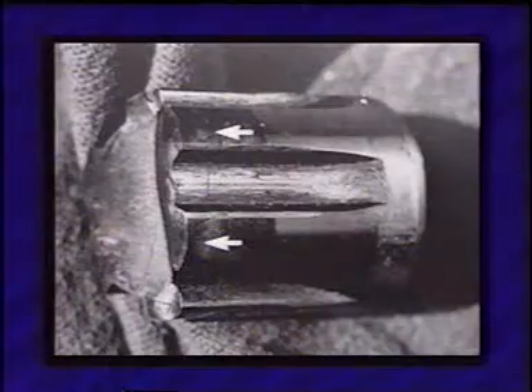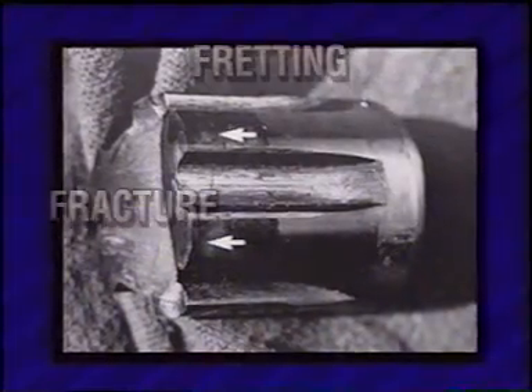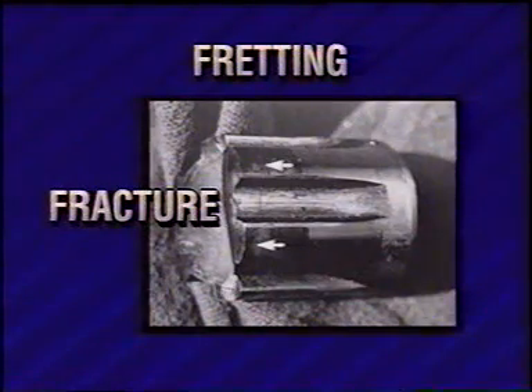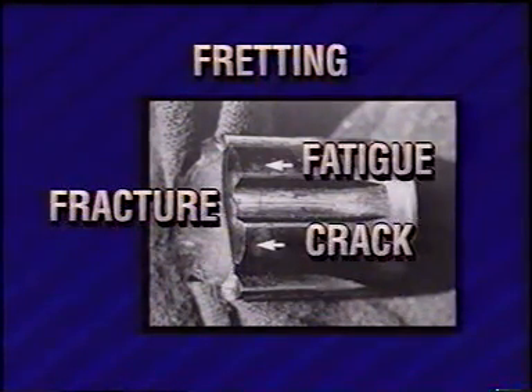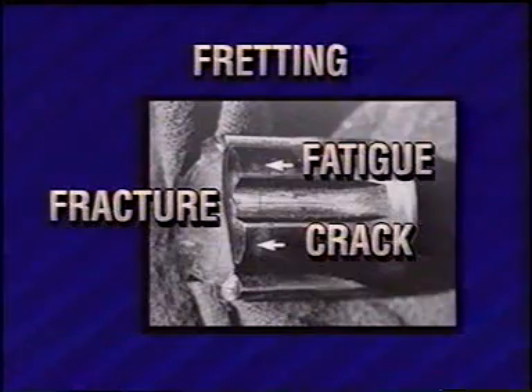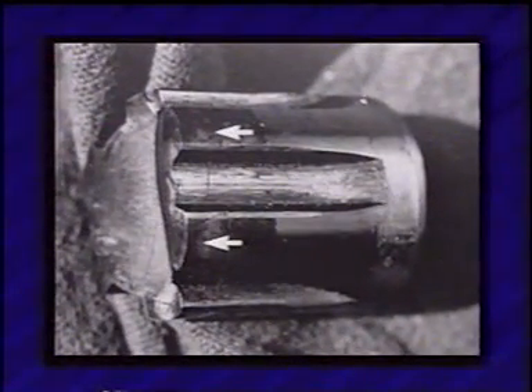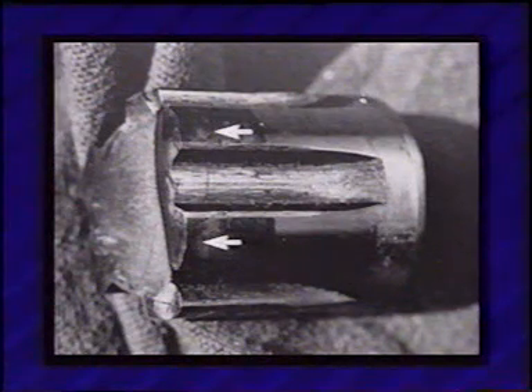One of the major problems with fretting is not the destruction of the joint itself, but the fact that it frequently leads to fatigue cracks and fracture originating at the interface. In many cases, the site where the fretting fatigue originates is different from the expected location of fracture. This is particularly true if the expected failure location has been strengthened by heat treating or mechanical pre-stressing of the surface. This steel spline shaft shows a typical fatigue fracture resulting from fretting on the surface.